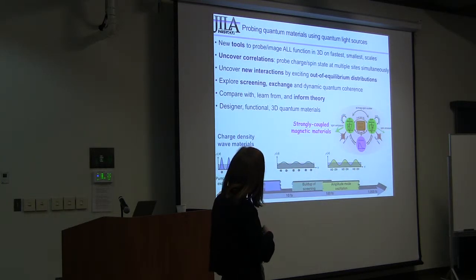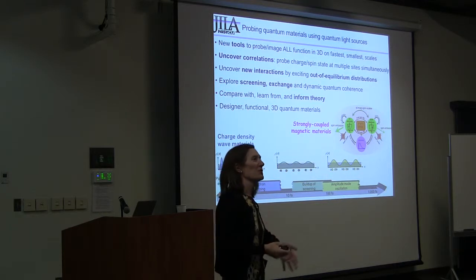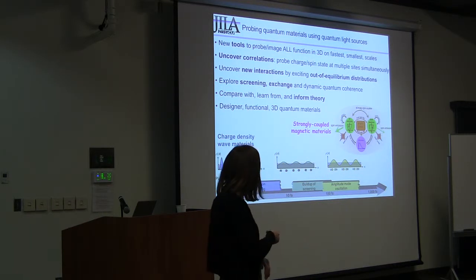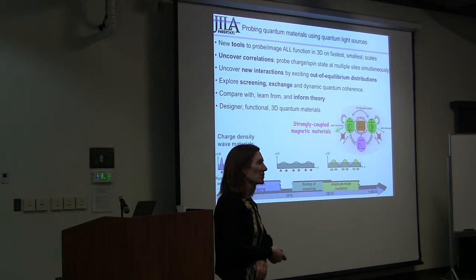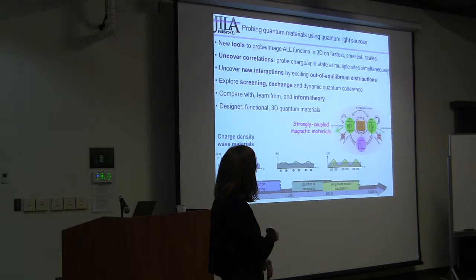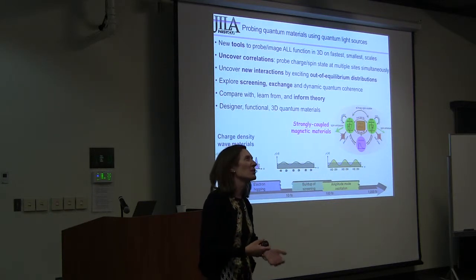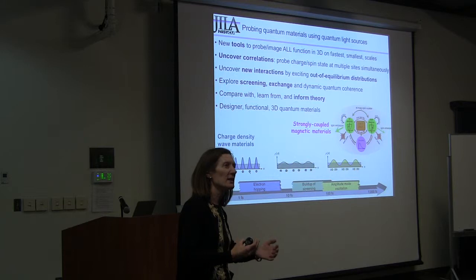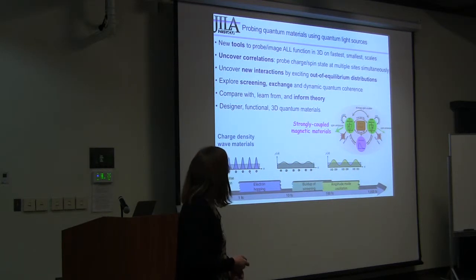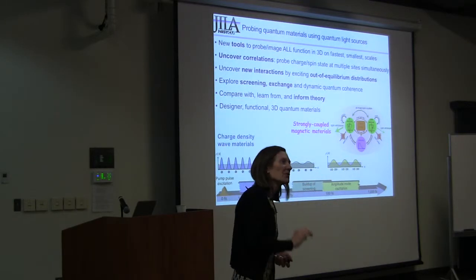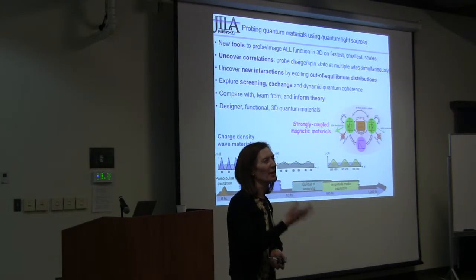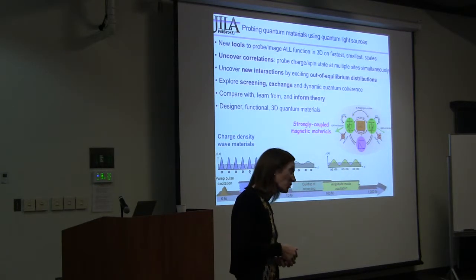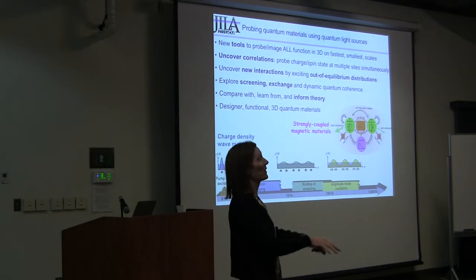So this is the sort of thing, for example, where quantum materials are of interest because they have very strong correlations. So if you've got these funny charge density wave materials where there's such strong electron-electron interactions that you can have charge ordering, and then at higher temperatures you get a metallic phase and an insulating phase. And sometimes in these materials it's hard to know why it is an insulator. You might expect it to be a metal, and by essentially pumping the material with a femtosecond laser and then looking at the band structure using photoelectron spectroscopy, and measuring the response time, you can learn why.